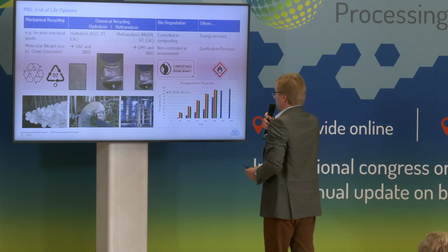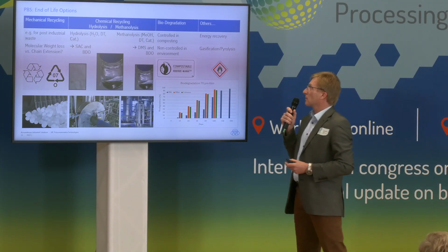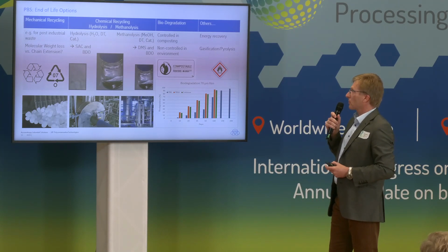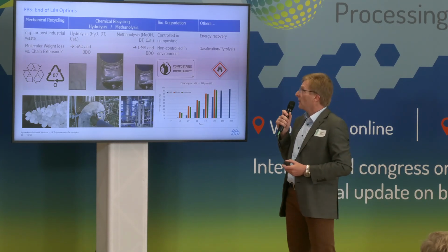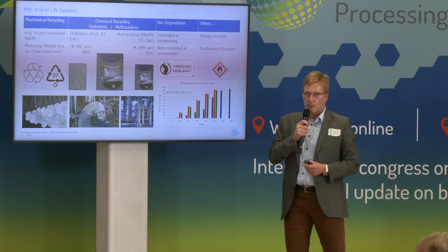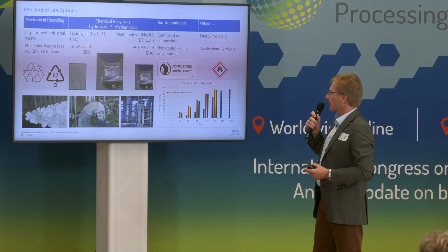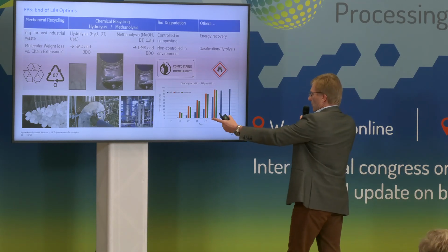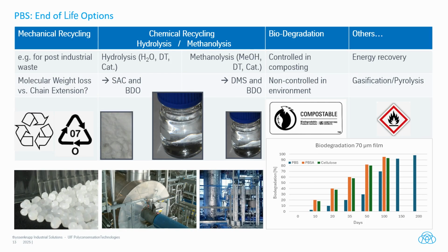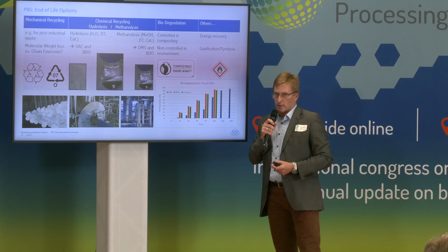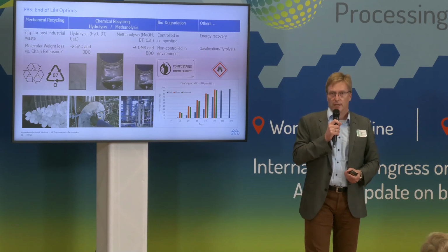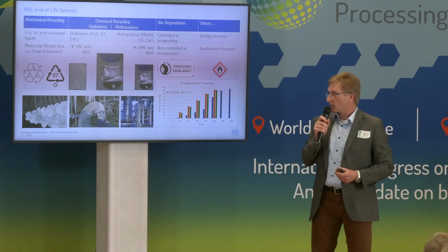We heard this: PBS is biodegradable. It's possible to do controlled composting in industrial plants, but it's also biodegradable in your home composting facility. And if you look at the composting rate of PBS compared to cellulose or PBSA, it's a little bit less, or it takes a little bit longer compared to cellulose in composting, but it's still very quickly decomposing after 100, 150 days, which is much, much faster than what we know from PLA, for example.